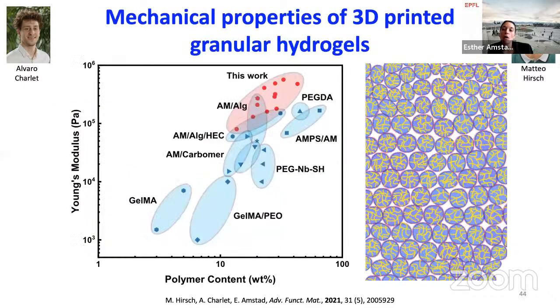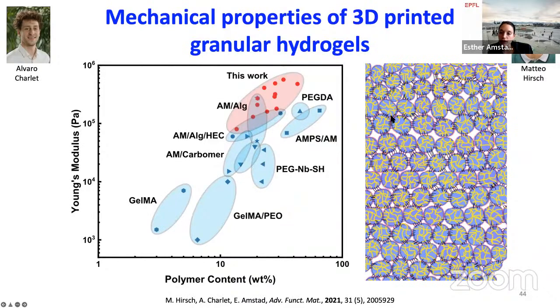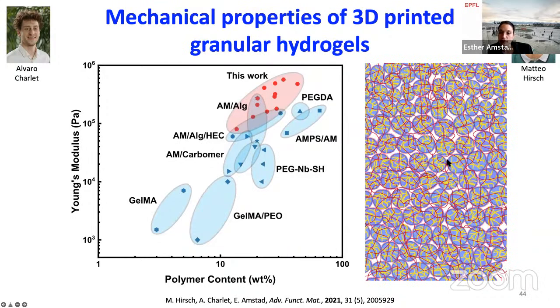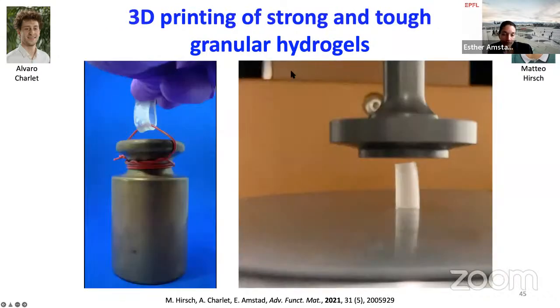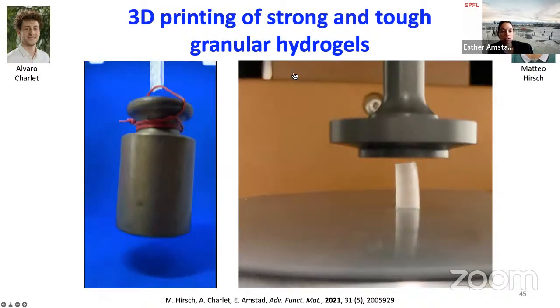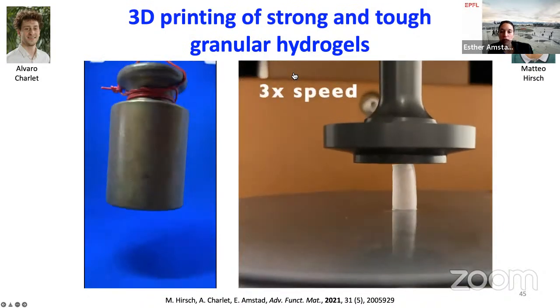And because now we connect these particles, not only through their interfaces, which has been done before, but through a percolating network that distributes the stress much more homogeneously, we actually could increase the stiffness of these materials by at least a factor of 4. So we could really use it for load bearing applications under tension as well as under compression.